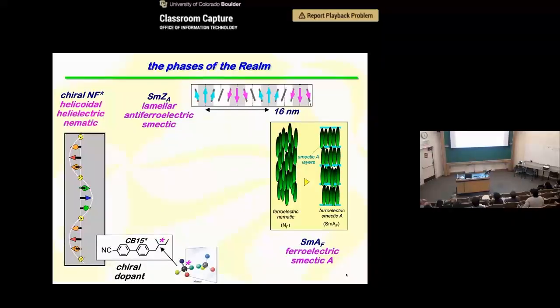So this induces the director to spontaneously form a helix. So this is like a chiral nematic, ferroelectric nematic. So CB15 is the chiral dopant. It has a carbon. This tetrahedral carbon has something different on its four branches. So this is a molecule. This molecule is not superimposable on its mirror image. So that chirality, that handedness, is expressed in the macroscopic structure of this phase.